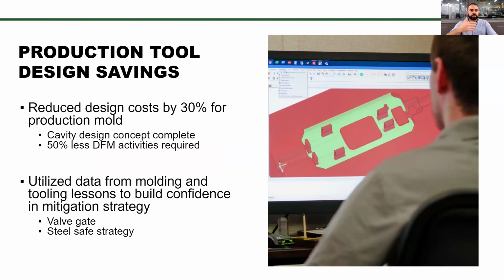Circling back to what was missing with Westminster Tool and why we added the 3D printer, this was the perfect case study to show the importance of having whoever's going to build your production tool involved in your front end. We learned that we needed A-side ejection on this part. Originally, we just printed it and said, okay, no issues. As soon as we put it in the press, the part was sticking to the A half. So we were able to add this to the cavities, or the advanced prototype cavities.